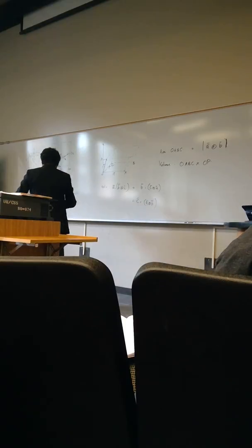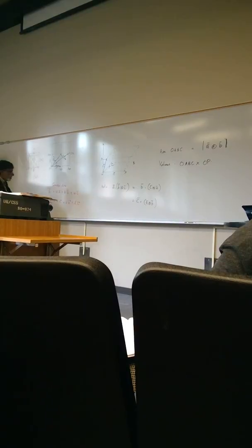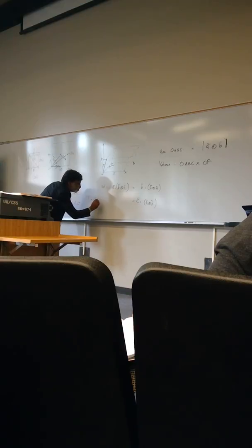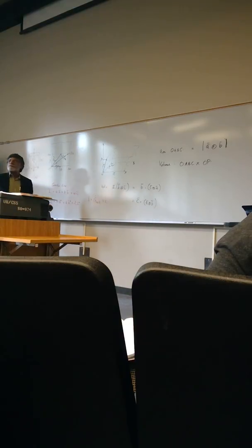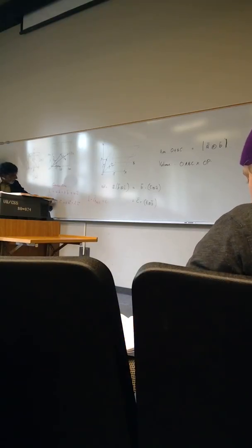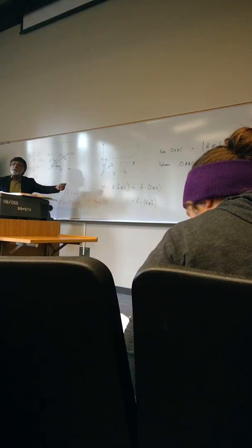So let's call this line L. The dot product is also a scalar product. So L dot G_HKL should be equal to 0. And therefore, U times H plus V times K plus W times L should be equal to 0.